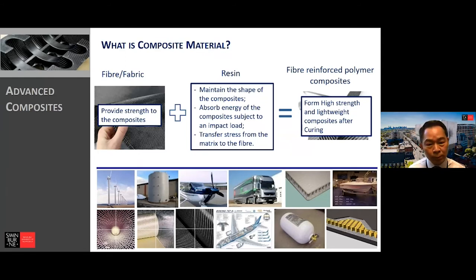And then the most important thing is that the resin can transfer the stress from the matrix to the high strength fiber. And after they form together, we form a very high strength and lightweight composite material after curing. And the curing we're talking about is 24 hours in general, but depending on what polymer you use, thermoplastic or thermoset. And thermoset is the common type of resin used for aircraft, but now there's more of a tendency to go to thermoplastics.